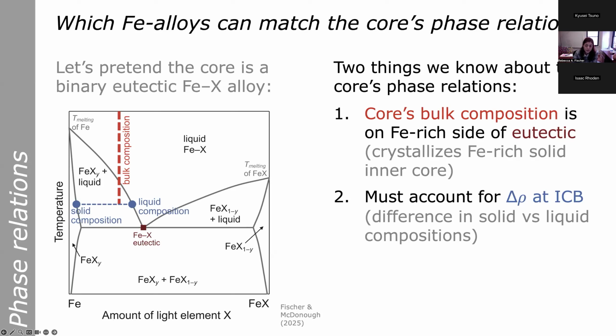We know that has to be true because that's how you crystallize an iron-rich solid, like we have as the inner core. If we were on the other side of the eutectic, what's crystallizing would be more rich in light elements. The other constraint we have on the core's phase relations is the density contrast at the inner core boundary. The density jump that we see there must be explained by the difference you have between solid and liquid compositions, integrated over time as the core is forming.